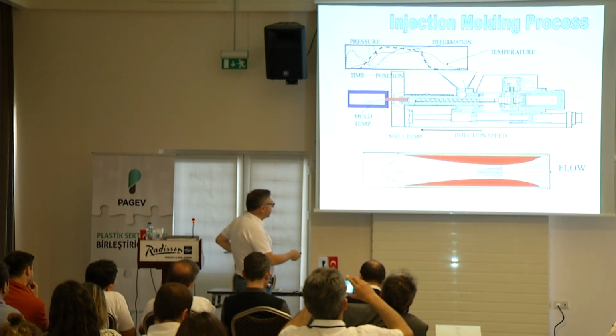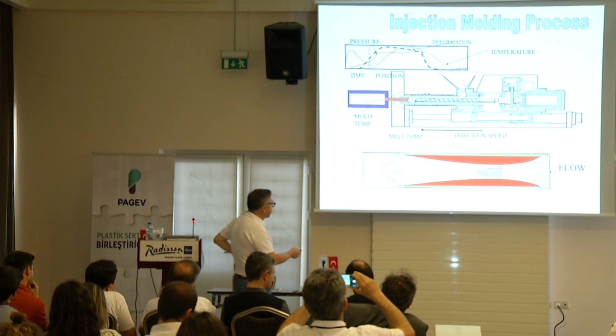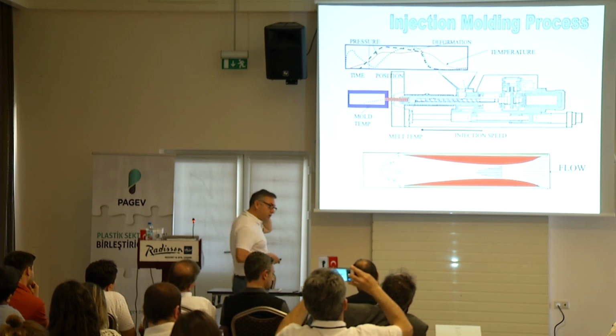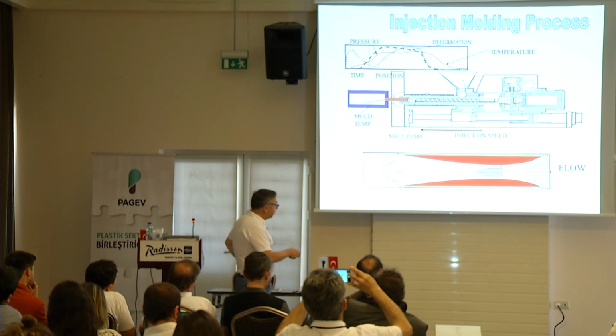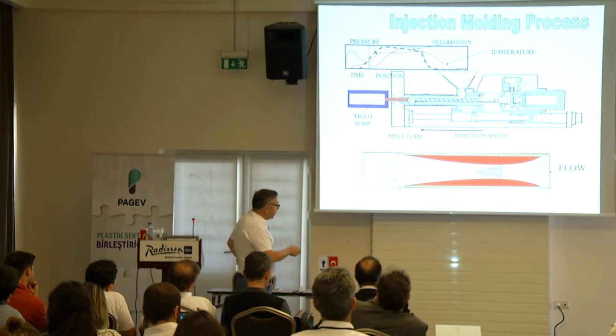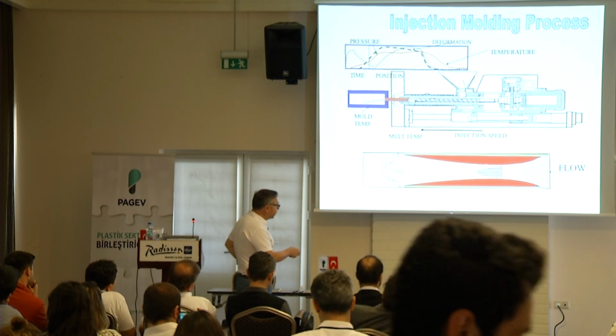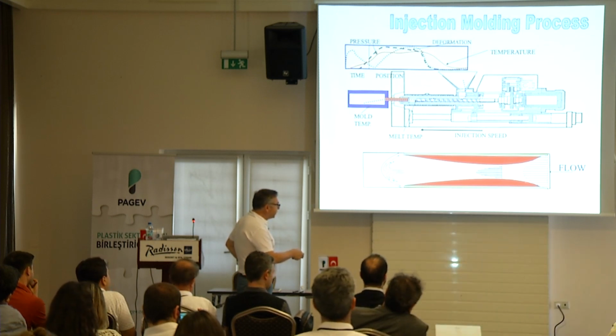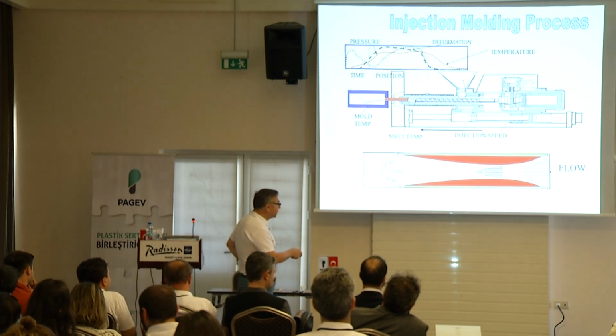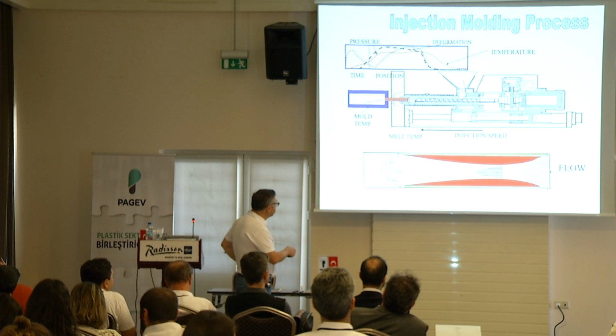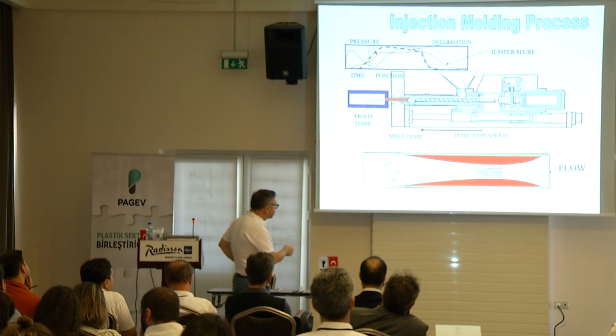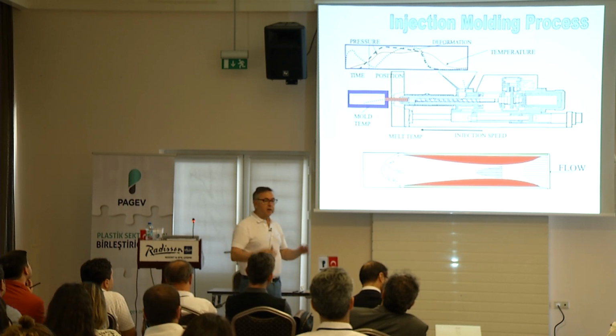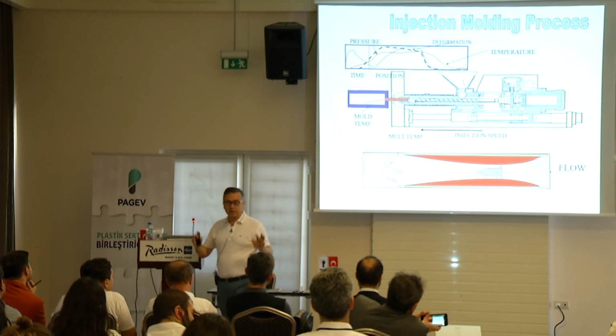What happens is that you have a dramatic change in flow geometry, because the red region is basically a solidification front that is approaching from both sides. And when they do, it also influences the local flow field, right? Here we have a gentle shear, but here it's a pretty sharp shearing flow. And this is called the fountain flow. And most people don't appreciate that those yellow skin regions are formed of material that has undergone biaxial stretching. This is literally like blowing a rubber balloon. It's a biaxial stretching.